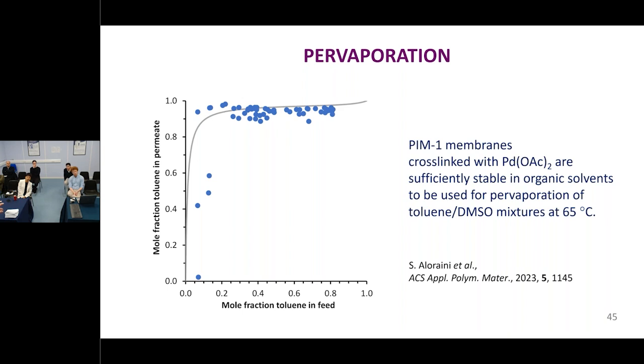Now, the beauty of a PIM is also its downfall. The beauty of a PIM is that it can be processed to form thin films and things, because it will dissolve. But something which will dissolve once will dissolve again. So the very feature which makes it processable is also potentially a weak point if we want to use it with certain solvents. I mentioned that we looked at pervaporation, and we're very interested in organic mixtures, but there are many solvents in which a PIM membrane isn't stable enough when you just cast it. But if we can cross-link it, we can stop it swelling too much.